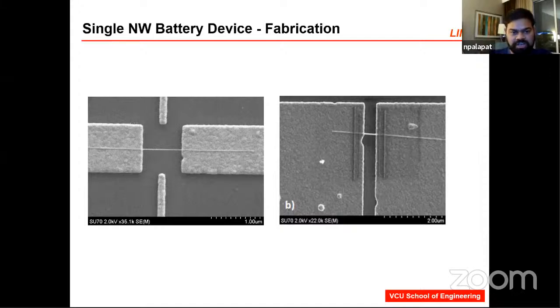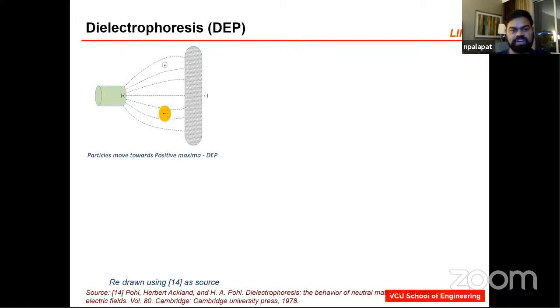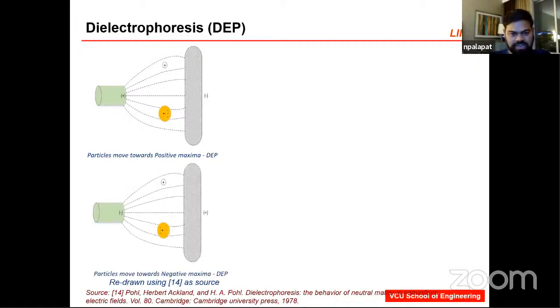So the question is, how am I able to deposit these nanowires? I've used a technique called dielectrophoresis, or DEP for short. DEP is if you place any polarizable particle in a non-uniform field, and depending on the field that you apply, either strong positive or strong negative, these particles can experience a dipole and thereby be attracted towards one side of your electrode. Either you want it towards the positive or towards the negative. This whole process is called dielectrophoresis.